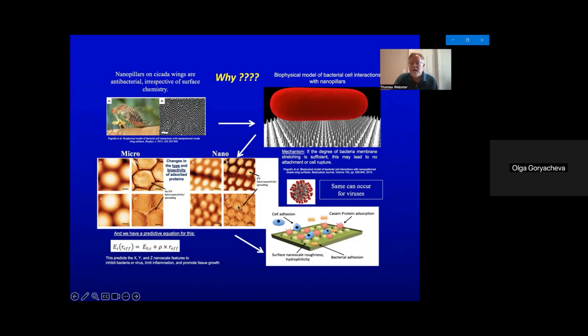In fact, the texture creates a more nanofibrillar fibronectin structure. This is more bioactive. It exposes more amino acids for cardiomyocytes to attach to. In contrast, over here, the fibronectin adsorbs like a hemispherical orientation, which is not bioactive. So you can use nanotextures to adsorb the proteins you want to get the cell response you want. And incidentally, it can also make the protein more bioactive after it's adsorbed.